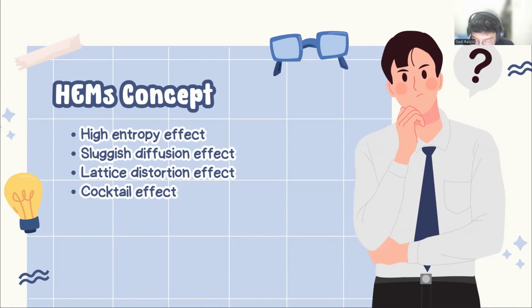HEM with solid solution possess many advantages, making them highly promising catalysts. Firstly, their wide compositional range allows for the adjustment of their electronic properties to meet the needs of catalytic reactions. Secondly, the isotropy and uniformity of HEM ensure that active sites are in the same chemical environment. For HEM catalysts, their single phase properties and absence of surface element segregation ensure a uniform distribution of catalytically active species, which supports the development of HEM catalysts with high selectivity. Moreover, the high entropy effect is considered the key factor behind the stability of HEM.